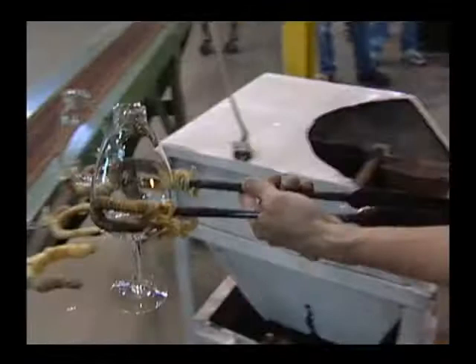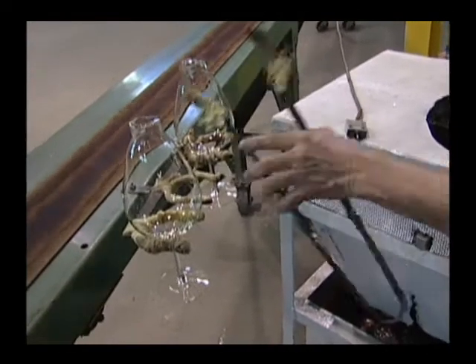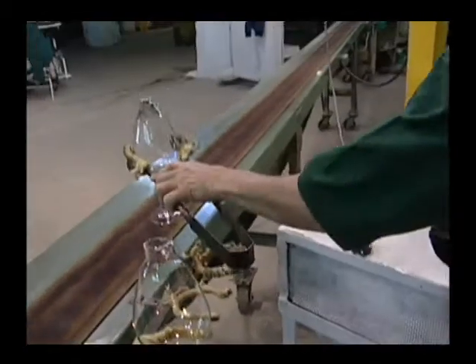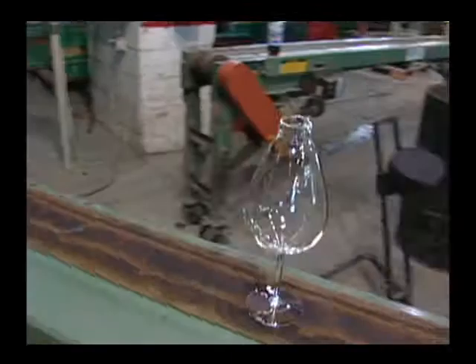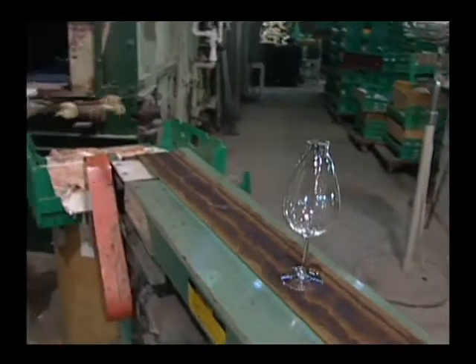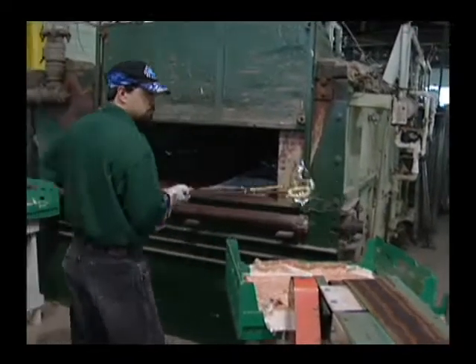The rapid cooling of the glass from its molten state develops stress in the piece, which must be relieved before further processing. That's accomplished through an annealing process, which reheats the glass and then slowly cools it in an oven called a lehr. This 90-minute process relieves stress and prepares the glass for the first of four quality assurance inspections.